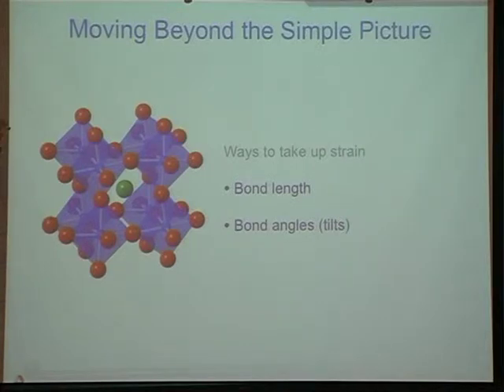in the first one I showed you a cubic material. These materials are really not cubic. Very few of them are cubic. They're often rhombohedral, orthorhombic, and this means the bond angles are not 180 degrees. They're often very tilted.